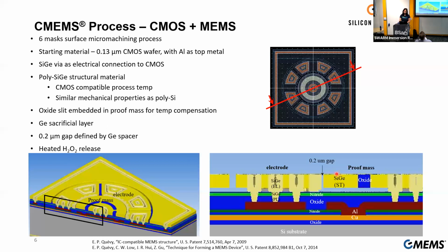From this cross-section image, you can see that we have the aluminum top metallization from the CMOS wafer. And then we use a silicon germanium via as electrical connection. This involves a plug layer and then later an electrode layer, so there were two depositions here. And then the slightly brighter color is the structural layer of silicon germanium. So we make a connection to the plug, the electrode, and then to the structure.